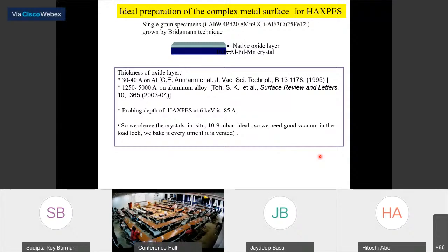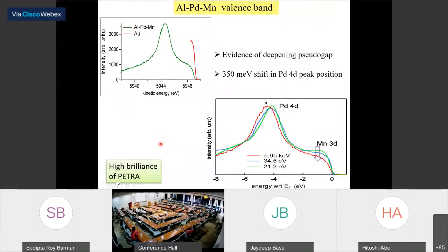So this is a typical survey scan of Al-Pd-Mn, and if you look at these nice peaks, these are all there. But our interest is in this small region, which is called the valence band. And this valence band requires the high brilliance of PETRA, and this is a typical valence band. You can see this valence band has a peak which is related to the palladium 4d states. And if you look at this part here, you can see that the intensity is coming down as you change the photon energies.